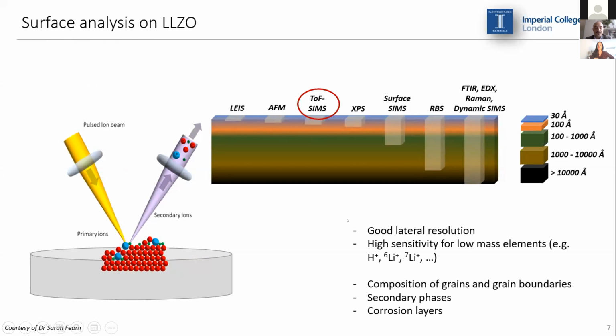So the advantages of using TOF-SIMS in lithium-containing materials, first of all, are good lateral resolution, so we can have information, for instance, on the composition of grains and grain boundaries and so on. But most of all, SIMS has a high sensitivity for low-mass elements, so we can detect and follow lithium on the surface of our samples. In that way, we can get an idea of different compositions, presence of secondary phases, corrosion layers, and so on.